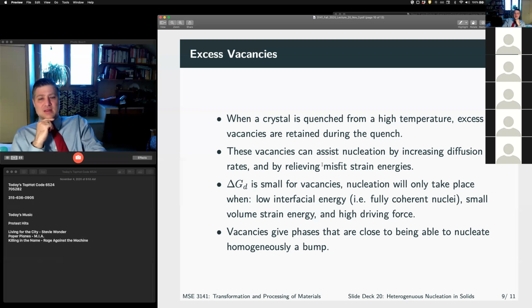Same thing with vacancies, except the energy of a vacancy is much lower than the energy of a dislocation, right? However, we do get increased diffusion rates when we have a large number of vacancies, right? So that means phases that would nucleate homogeneously, such as the GP zones in aluminum, are going to get a bump, right? They'll nucleate faster because of a large vacancy content, right?